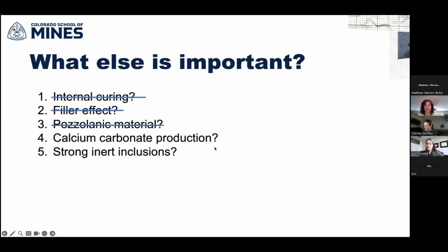One is calcium carbonate production, which I'll talk about a little bit more in the subsequent slide. And then the other one is just strong inert inclusions, where you've got some strong carbon mixed into the cementitious composite, and you're just getting kind of a composite effect. I think there is less evidence for this last one, particularly since we have some data indicating that we do get a denser final product. So it does seem like there's something else happening that's causing densification, and we just haven't found the smoking gun yet.